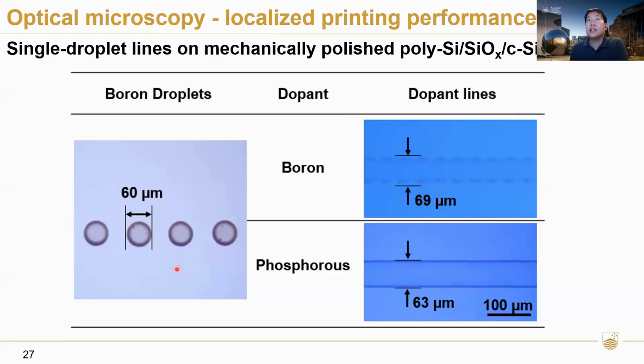So the first image here is an optical image of the boron droplets when they're not touching. We see that each droplet is about 60 microns. There is some leeway to change this value, making it smaller or larger by changing the viscosity, for example, or the printing voltage. But if we decrease the gap between each of the dots that we print, then we start to see the dots overlap. In this case, we see a boron diffusion line, the boron glass line, and the bottom is a phosphorus line. In both cases, they are about 60 to 70 microns wide.